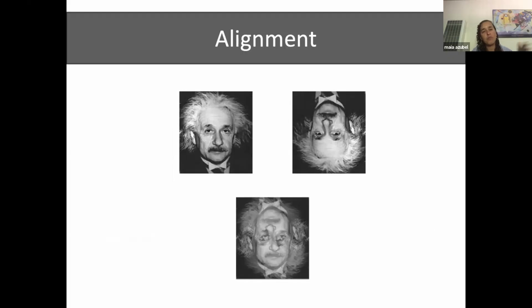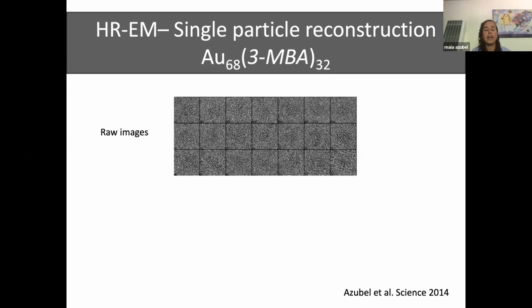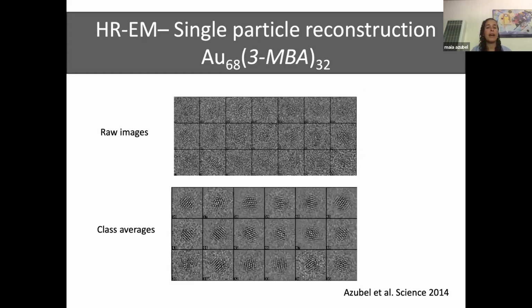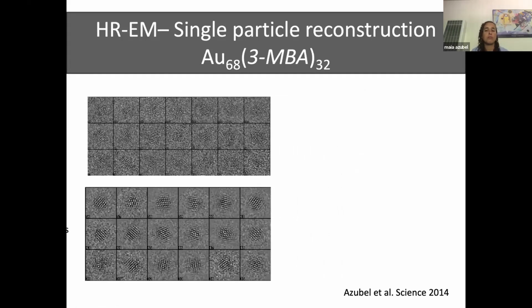And even though the software has changed quite a lot since 2015, I believe that was when, or 14, when we published the structure of gold 68, the same principles apply, okay? So here again, we have the raw images. Hopefully now that I'm showing you the averages, you can see a little bit better the atoms because the noise of the background gets canceled and you increase your signal to noise ratio. And those are the classes that we use to produce the 3D structure.